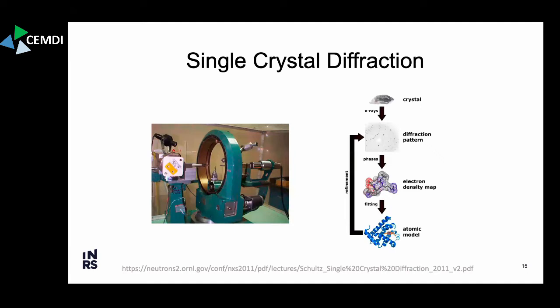So I wanted to start by asking, who's ever done a single crystal diffraction experiment, X-ray or neutron or anything? Okay, so we have some experience in the room, very good. For those who aren't familiar, normally how this goes is you have a sizable single crystal. You can see it, and you put it on a goniometer, and you can rotate this in all three directions in space, and you have a source and a detector over here, and you measure the Bragg reflections throughout all of the different orientations of this crystal. Whenever you rotate the crystal, you change which Bragg reflections you obtain.